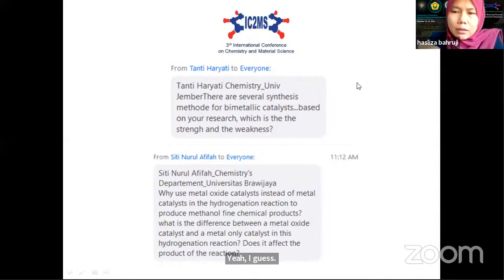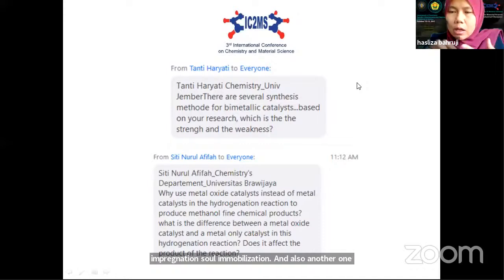From my research that I discussed with you just now, the catalysts that we produce use impregnation, sol immobilization, and also chemical vapor deposition. All these methods have their own benefits and disadvantages. The benefit of impregnation is that it is very easy to do: you just mix the catalyst, dry them, and calcine them. But the problem with the impregnation method is that your catalyst tends to sinter.